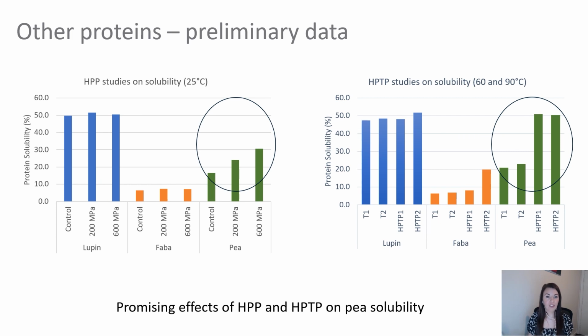And I did just want to touch on the other proteins that I mentioned, so lupin, faba, and pea. On the graphs here, you can see we have our high pressure processing study at ambient temperature and our high pressure thermal processing study at 60 and 90 degrees Celsius. We have two temperature controls, T1 and T2, and high pressure thermal processing, one with 200 megapascals and two at 600 megapascals. And as you can see, really with that high pressure thermal processing study, we're getting a big increase in pea protein solubility. So this really does warrant more research, but it's quite an exciting finding.